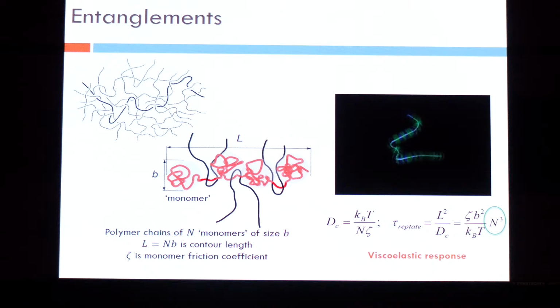So if I have a polymer molecule now that contains n of these blobs, and each blob is of the size of, let's say, B, then n blobs times B size is the length of my polymer chain. So that's L. And then each of these blobs is moving in this constrained environment, and because it is connected with many neighbors, as it moves around, it encounters friction. Just like if you move around in a very packed vehicle, you will feel the friction around you. So these molecules are also in a packed, entangled environment, and they encounter friction. And that is called the monomer friction coefficient. Based on this very simple picture of a polymer in an entangled geometry, one can work out many interesting things.